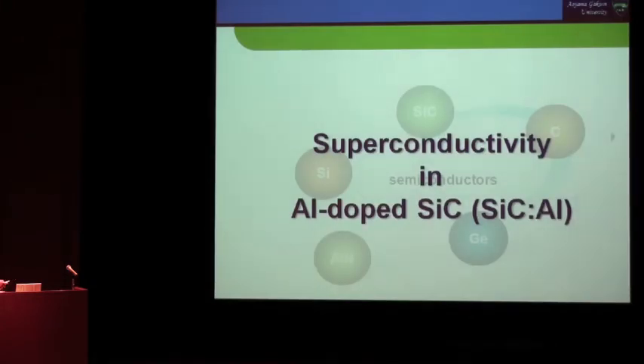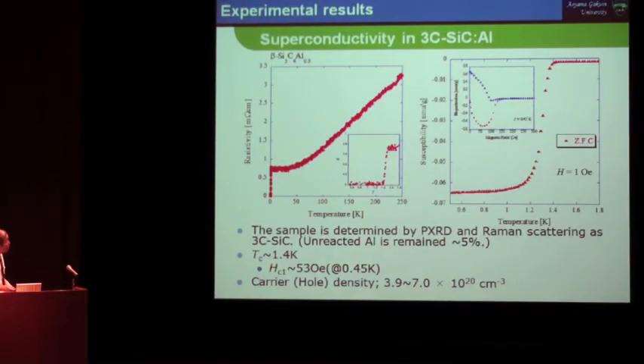Next step is superconductivity in aluminum-doped silicon carbide. This is data of the aluminum-doped silicon carbide here: this is resistivity and this is susceptibility. We estimate the carrier density is from 4 to 7 times 10^20 per cubic centimeter.